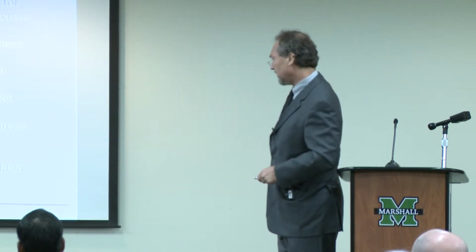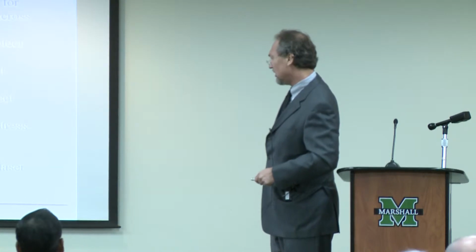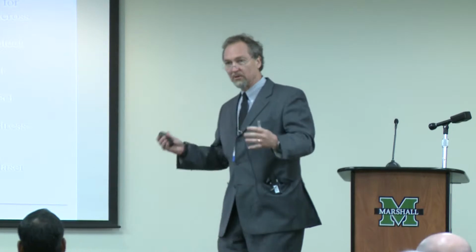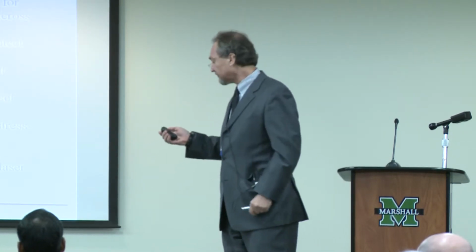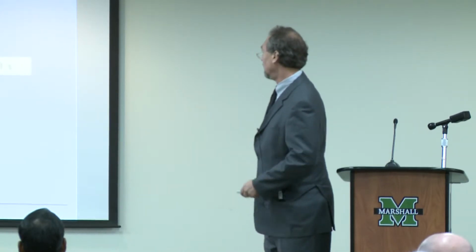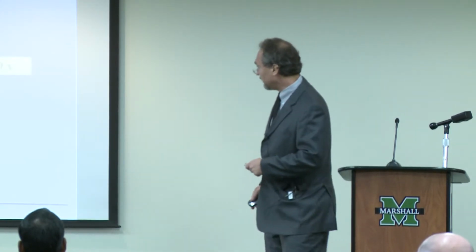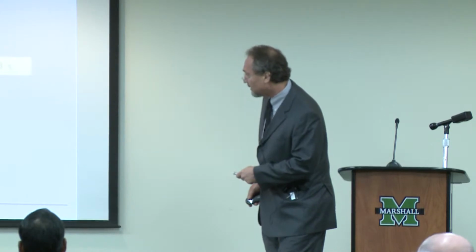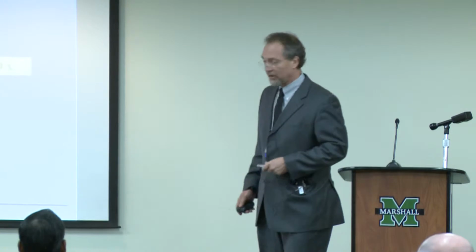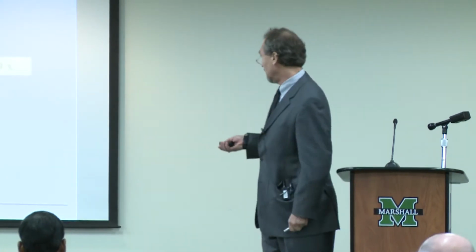Okay, and then also, because I've got this intense laser light, I needed a jig to do some things. I needed to protect it from the laser electrical discharge that's going on in the background. So that was a pretty key improvement. The superlattices, I've got 30 layers, 17.5 nanometers per charge sequence, and it goes positive and negative, and you get about 35 nanometers for the superlattice. These are grown on 6-inch wafers over at the University of Stuttgart at the Semiconductor Engineering Institute.